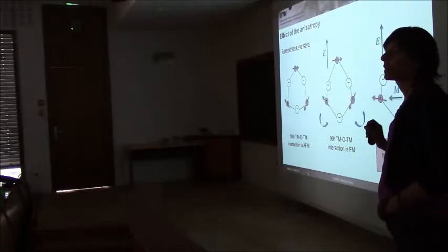The symmetry of my magnetoelectric tensor. So the magnetic anisotropy has changed the magnetoelectric response. Notice that this mechanism, in fact, doesn't require any mediation by spin orbit coupling. It's entirely just through the Heisenberg exchange. So it's a rather strong mechanism. It's going to be a very strong effect.